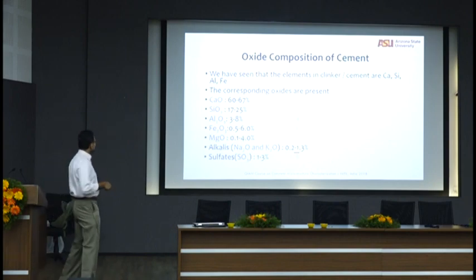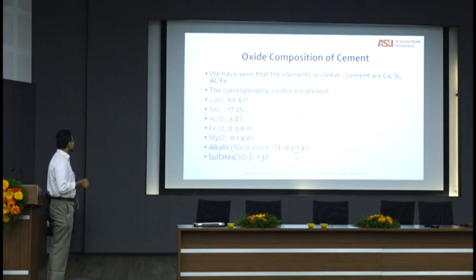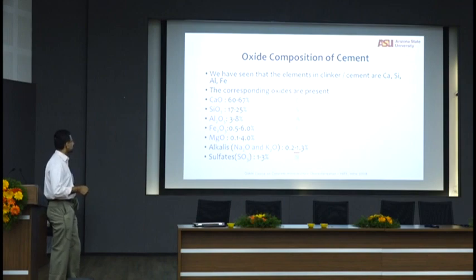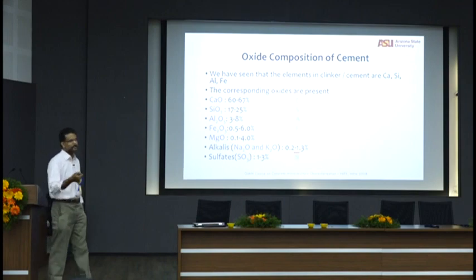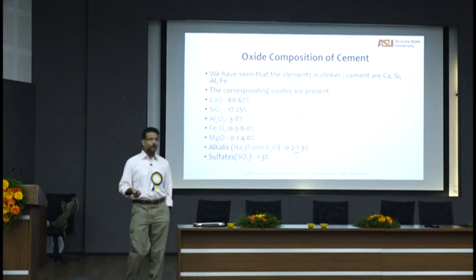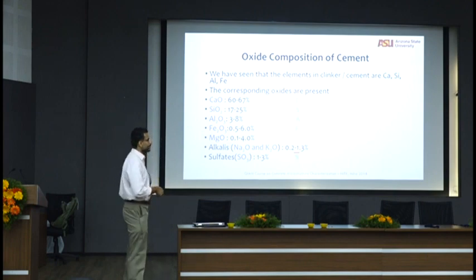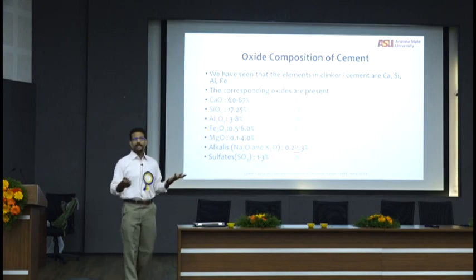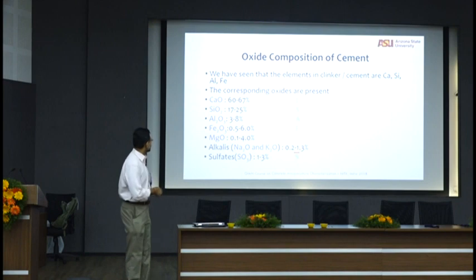Now, typical numbers, I think these are all over the world. Calcium oxide 60 to 67%, silicon dioxide 17 to 25%, aluminum oxide 3 to 8%, iron oxide 0.5 to 6%, magnesium oxide 0.1 to 4%, with issues with soundness if you have more. Alkali, sodium and potassium oxides 0.2 to 1.3%. Typically your IS standards or ASTM standards will ask you to keep it lower than 0.6. In India it's 0.65. In the US it's 0.6. Sulfates 1 to 3%. So that adds up, and that's all what you have in this very complicated material.